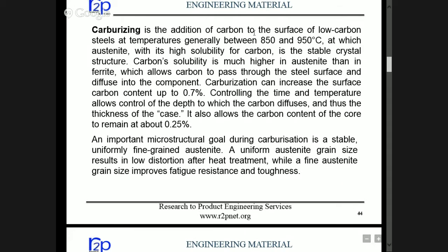So here the process is defined. The component is heated to 850 to 950 degrees centigrade for carbon buildup, while the phase is austenitic. And when the carbon percentage up to 0.7 is increased, then we hold it for some time and then do the quenching.